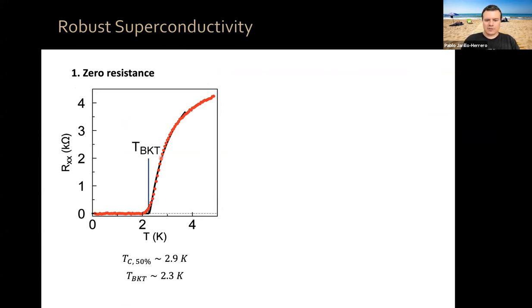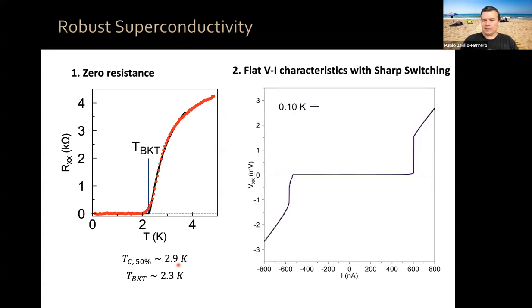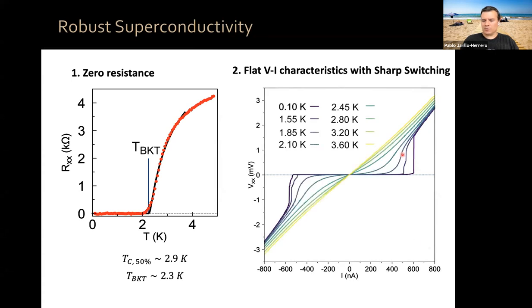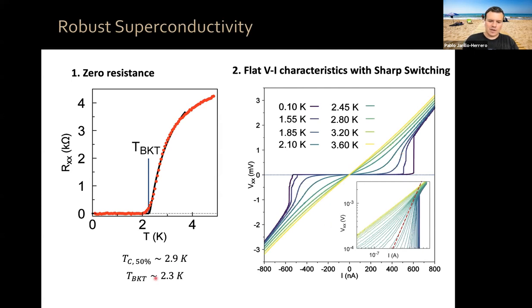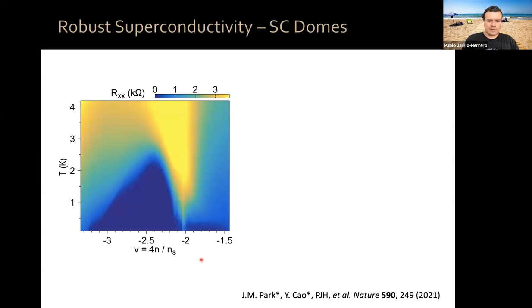TC at 50% normal state resistance, which is very often quoted in these two-dimensional superconductors, is about 2.9 Kelvin. You also want to see flat voltage-current characteristics with sharp switching. And indeed, here you go, at base temperature, very flat, sharp switching. You can do this as a function of temperature and do a BKT analysis of the voltage-current characteristics and extract the same BKT temperature. Now, this is an electrically tunable superconductor also, okay? So this is the resistivity versus filling factor in the region around 2 holes per Moire unit cell.